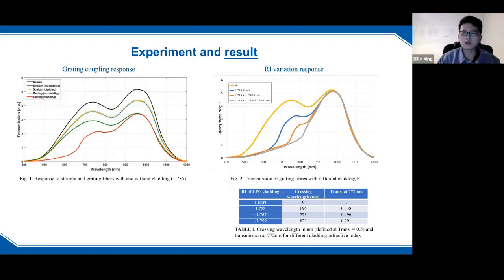After this experiment, we also did the refractive index variation response. In this experiment, we use different liquids, index oil in this case, with different refractive index values, to see if they can affect the grating and the transmission spectrum. It turns out it is very obvious, and the transmission actually shifted a lot. The cross wavelengths changed by over 100, from 696 to 825, and the intensity also dropped.